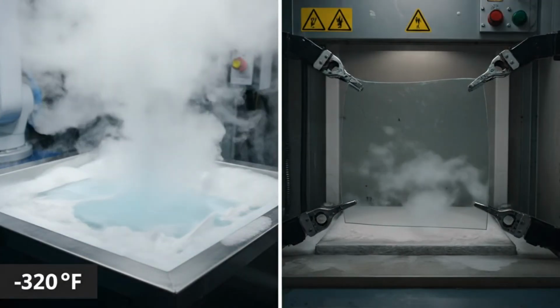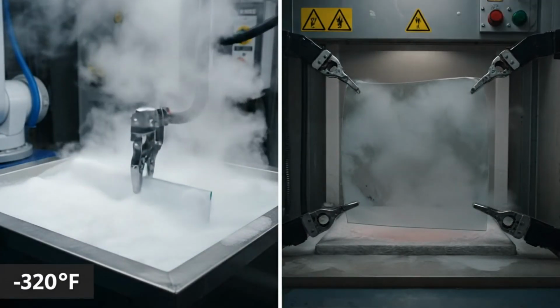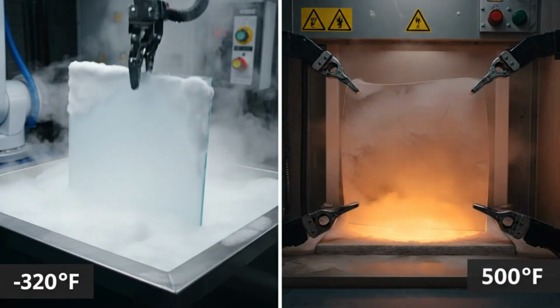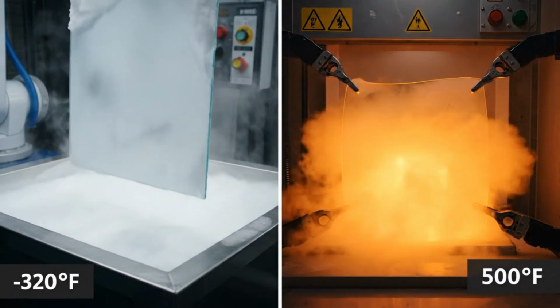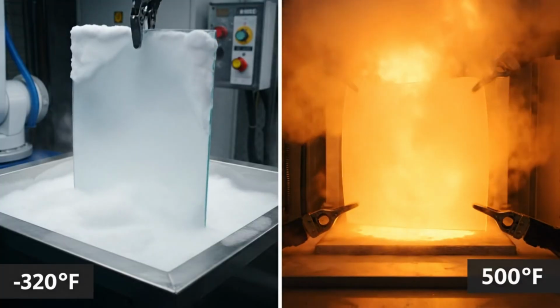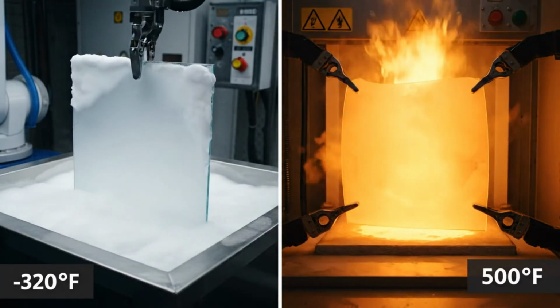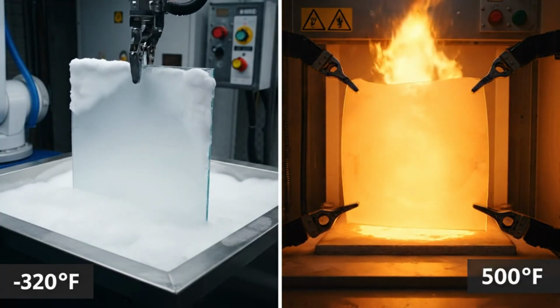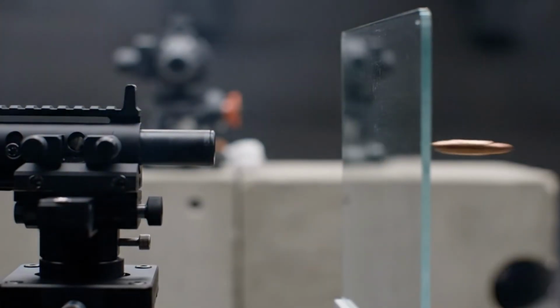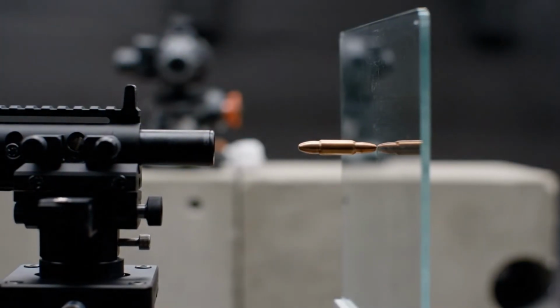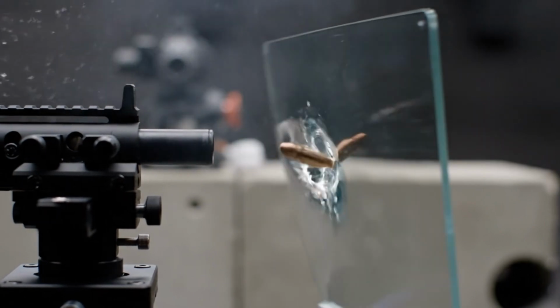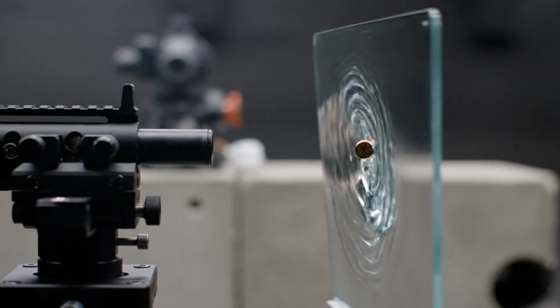Thermal shock testing is particularly brutal. The glass goes from -320 degrees Fahrenheit to 500 degrees in seconds. That's an 820-degree temperature swing. Normal glass would explode from the stress. We even test ballistic resistance. High-velocity projectiles are fired at the panels. The glass catches bullets that would shatter conventional glass.